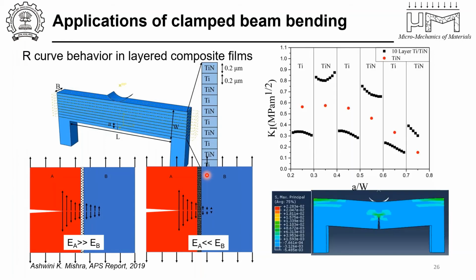So again, when you have a stiffer layer, the stress intensity factor that the material should see in front of the crack tip will go down, because it's sort of going to close the crack. Whereas when you have a compliant layer in front of the crack tip, it sort of opens the crack and the driving force will go up.